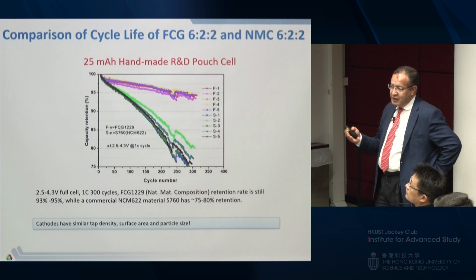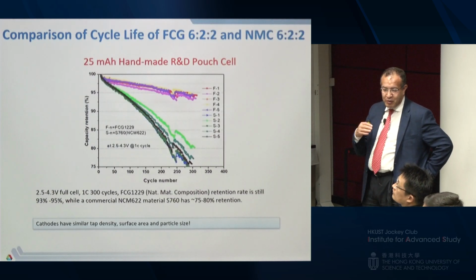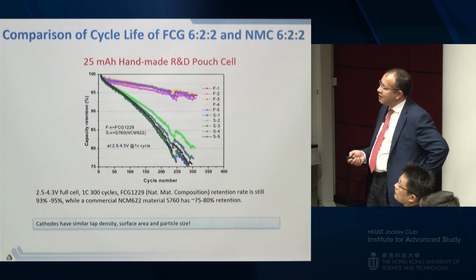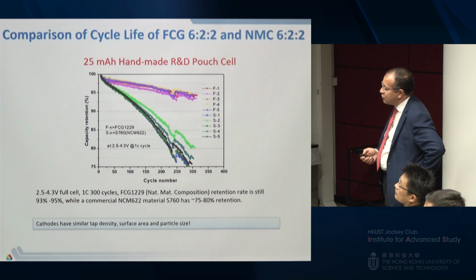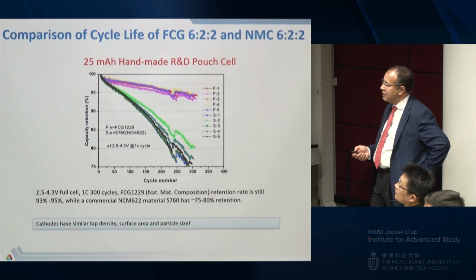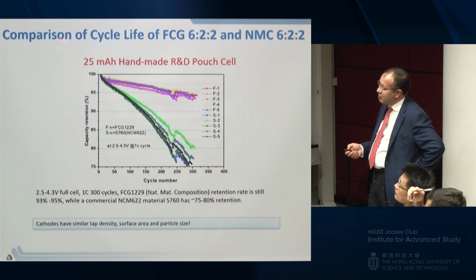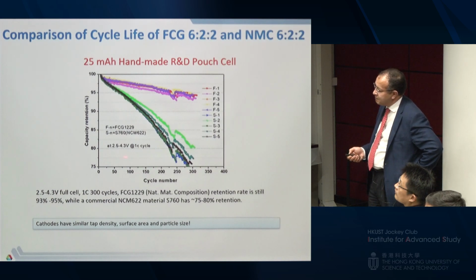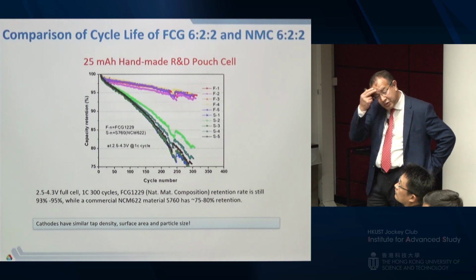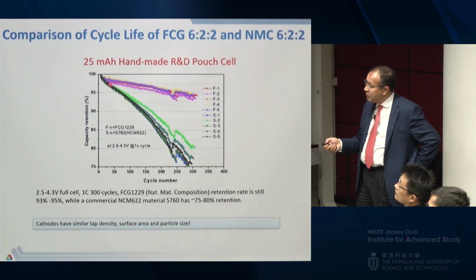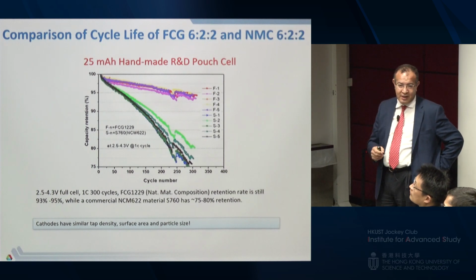So eventually after that, we start looking at what is the performance at the full cell. And this is a small 25 milliamp hour pouch cell we made at Argonne, and we compared the performance at 4.3 volt. You can see that the commercial one is dropping pretty fast. Within 300 cycles, we lost almost 25% of the capacity. With the new gradient, we have far much better result.